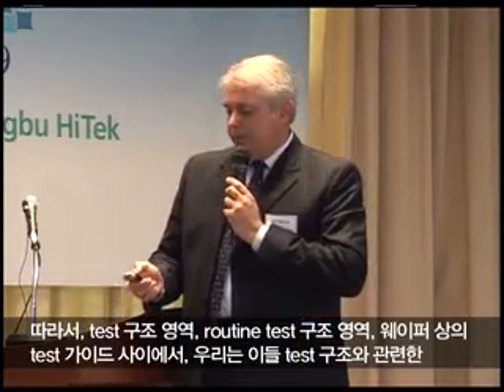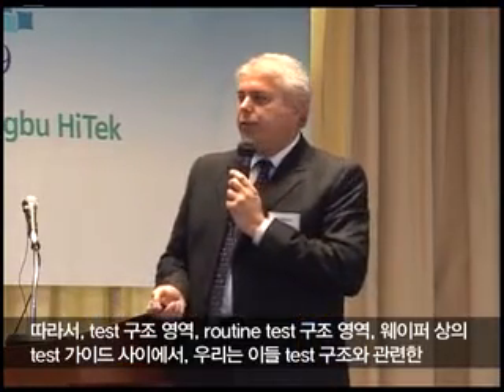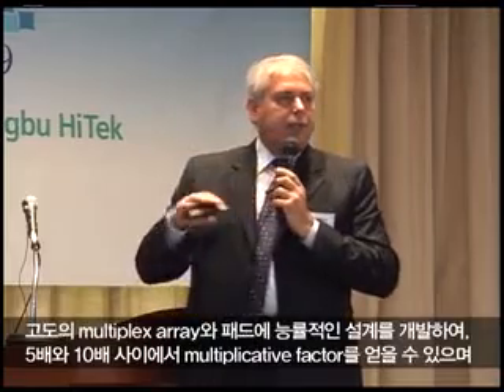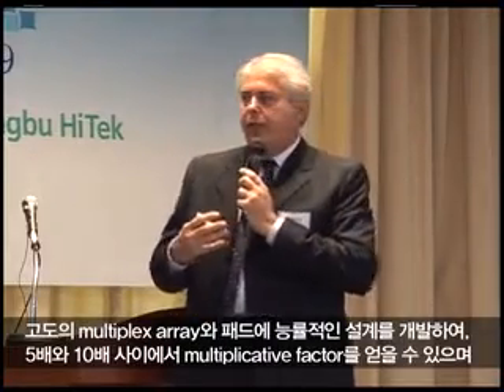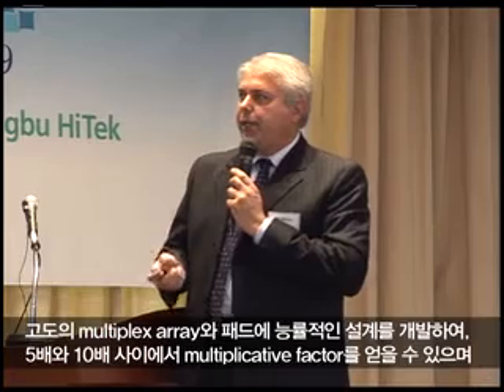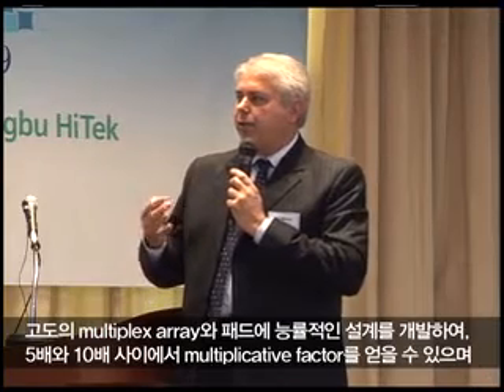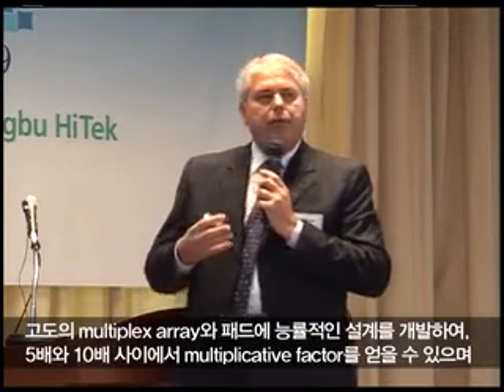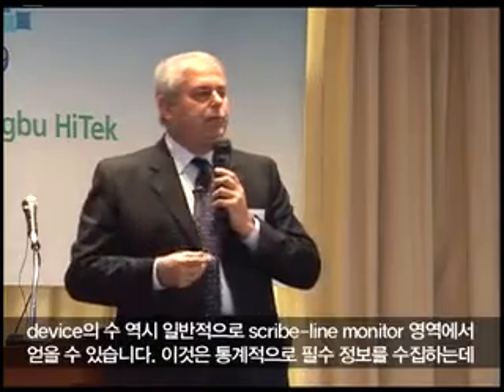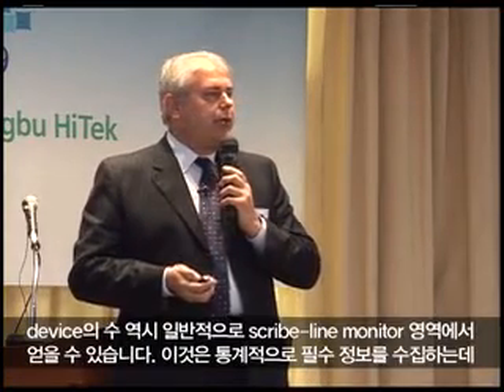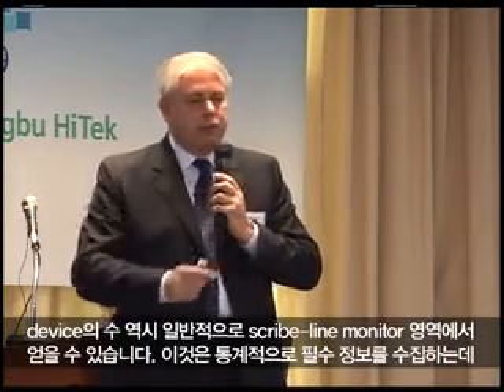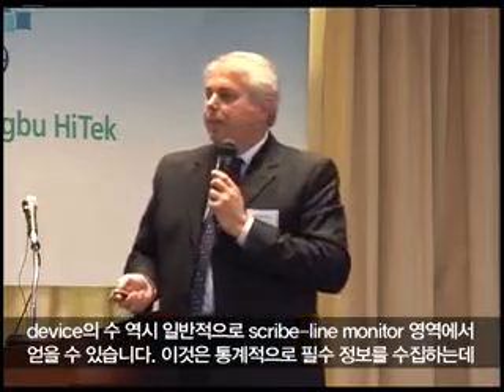But we've developed highly multiplexed arrays and pad-efficient designs for these test structures so that we can get a multiplicative factor of, let's say, between 5 and 10 times the number of devices that you would normally get in, we call it a scribe line monitor.